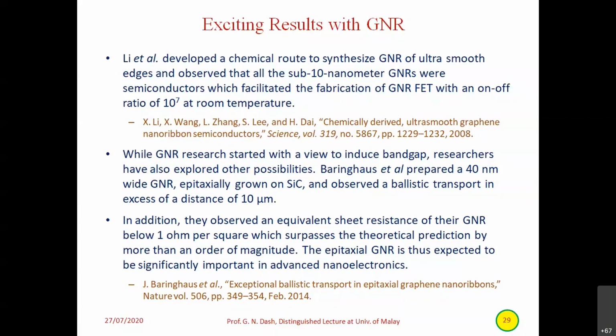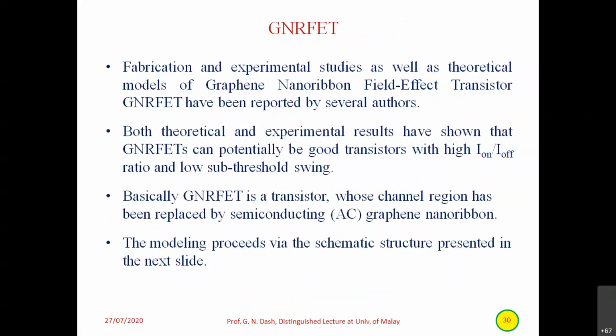Now, in addition, they observed an equivalent sheet resistance of their GNR below 1 ohm per square, which surpasses the theoretical prediction by more than an order of magnitude. The epitaxial GNR is thus expected to be significantly important in advanced nanoelectronics. Now, GNRFET application: experimental studies, as well as theoretical models of graphene nanoribbon, have been reported by several authors. You will see that the literature is zoomed with a number of papers, but theoretical and experimental results have shown that GNRFET can potentially be good transistors with high ION to IOFF ratio and low subthreshold swing. We know the subthreshold swing predicted for common semiconductors is 60 millivolt per decade, not below that, but GNRFET is much below that. We'll see.